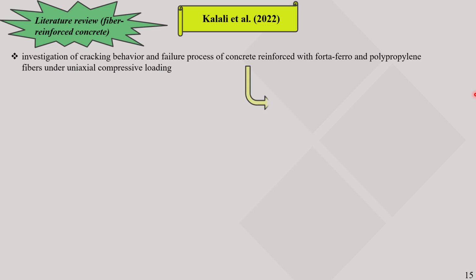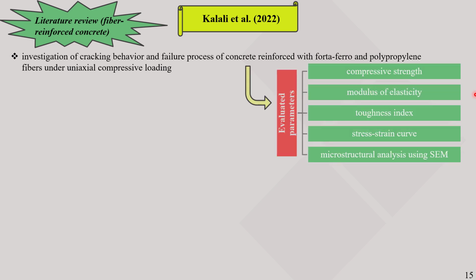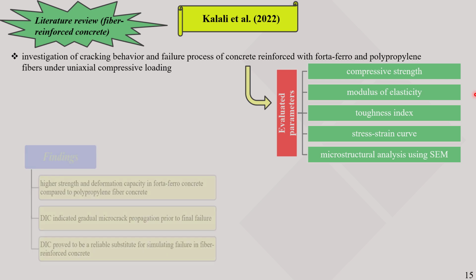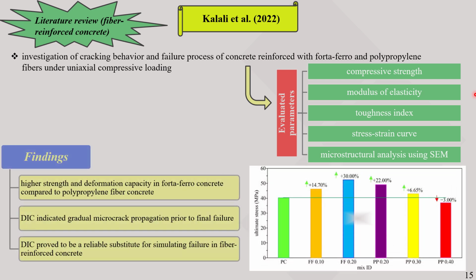The first article was by Mr. Kalali and his colleagues, which examined the cracking behavior and failure process of concrete reinforced with Forta-Ferro and polypropylene fibers under uniaxial compressive loading. They also evaluated several parameters, such as toughness index, compressive strength, and others. The most important finding was that the strength and deformation of concretes containing Forta-Ferro fibers were higher than those containing polypropylene fibers. The graphs from these experiments are also shown in this section.